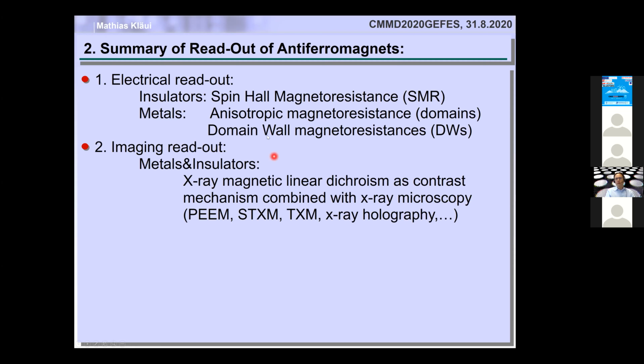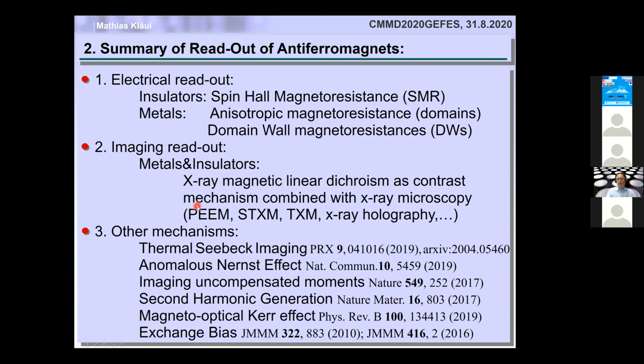For imaging, we can image these systems using X-ray magnetic linear dichroism together with some X-ray based microscopy, such as photoemission electron microscopy. And then there are lots of other techniques that I didn't go into today, such as thermal Seebeck imaging, there's some nice work from Cornell, anomalous Nernst effect imaging uncompensated moments, second harmonic generation, also magneto-optical Kerr effect, where we also did some work, and exchange bias. And there are also other ways. So actually right now there are a number of quite useful antiferromagnetic readout technologies.